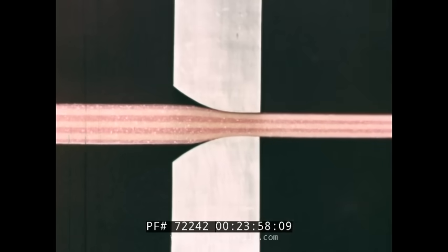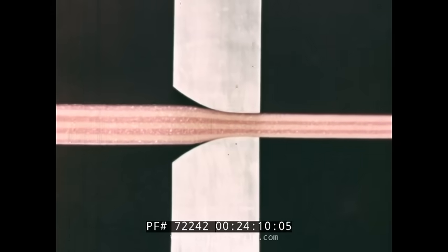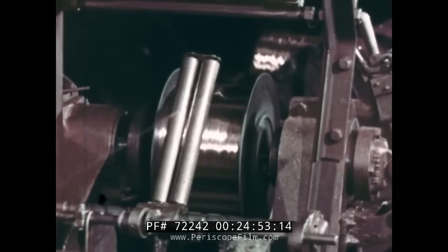Each die may make a reduction of, say, 30%, producing very high local pressures and temperatures. This tends to cause heavy die wear, and dies are therefore made of very hard materials, such as tungsten carbide and diamond. Even so, lubrication is of the utmost importance to keep die wear to a minimum. In modern continuous machines, capstans pull the wire through a number of dies in succession. For the finest gauges, the wire may have to be drawn through 30 or 40 dies.